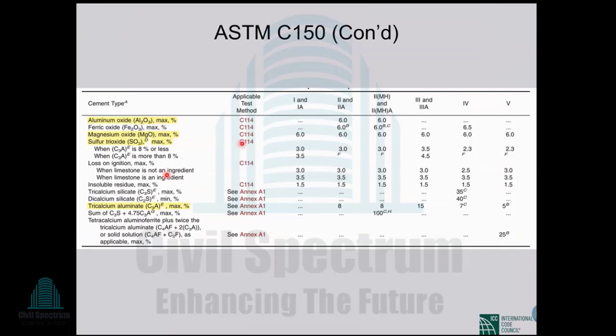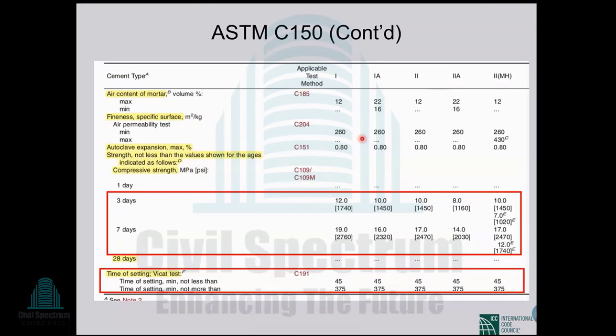Now, the chemical composition of these different types of cements are specified as shown in this table. So for type 1, what should be the maximum percentage of alumina, what should be the maximum percentage of magnesium oxide, or what should be the maximum percentage of other compounds. These are mentioned here. And the properties like fineness, expansion, etc. Among the properties, compressive strength is the most important one that is most often tested. You see, in ASTM, both 3 days and 7 days strength are specified for different types. For example, in our case, type 1 is equivalent to CEM1.